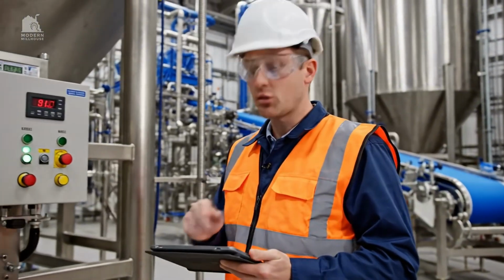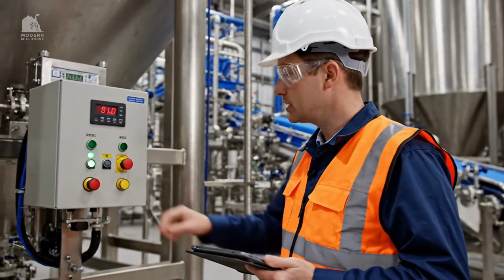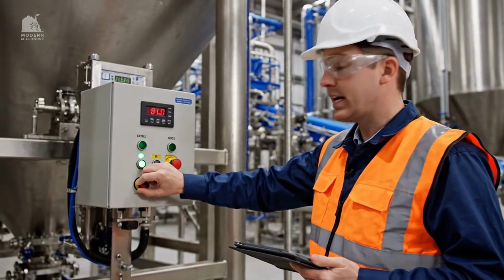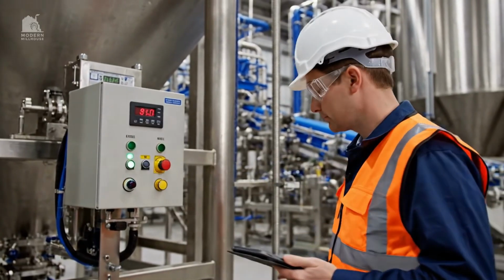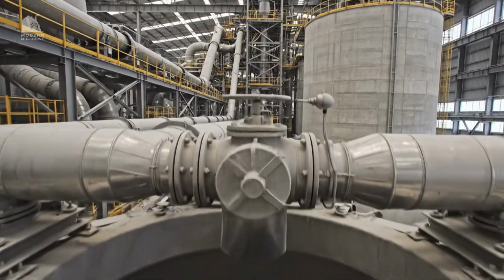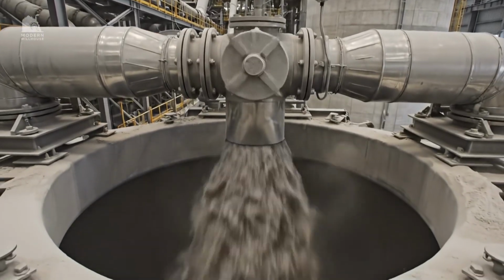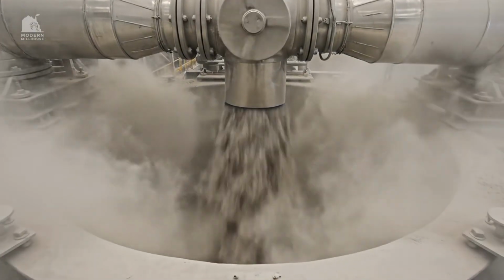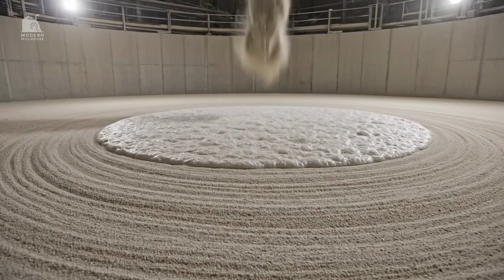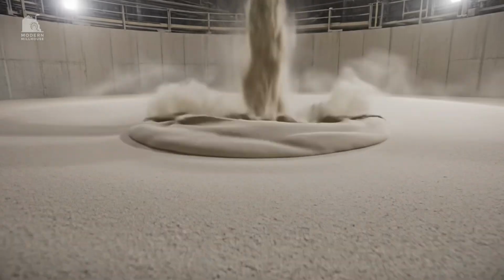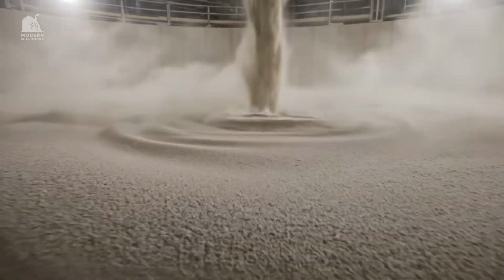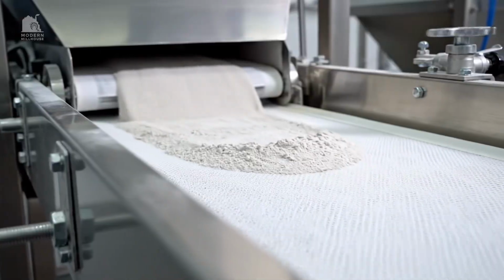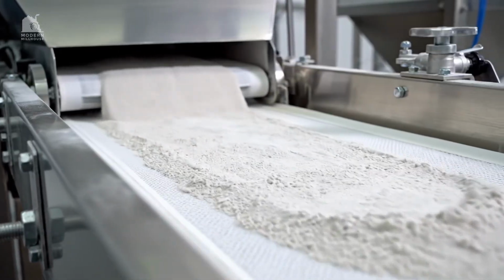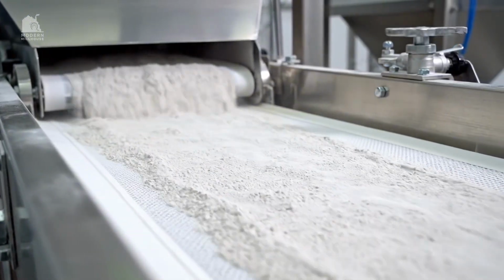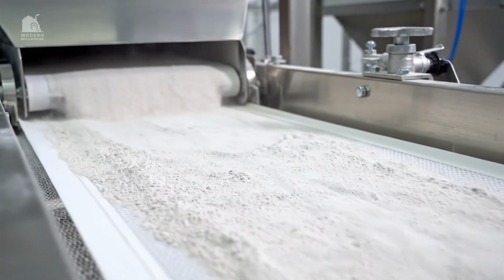Key targets include lime saturation and silica balance because they determine how easily clinker minerals form in the kiln. Once ground, raw meal moves by air slides and pneumatic systems, staying enclosed to avoid moisture and dust loss. Homogenization silos reduce chemistry swings, creating a steady kiln feed that supports stable burning conditions. Air slides move powder efficiently with minimal mechanical parts, reducing wear and keeping the material dry.